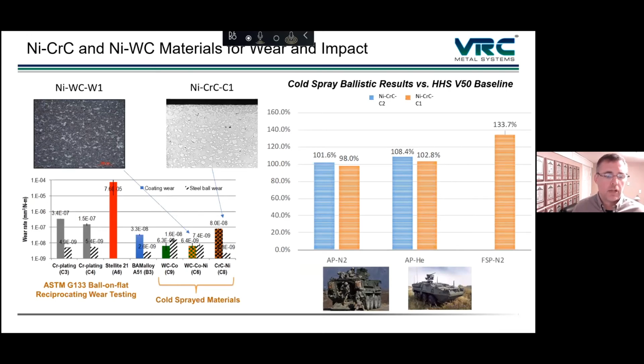ballistic performance as well. So this is repairing armor. This is high hard armor repair. And these are V50 type of tests, which means basically the 50th percentile will fail. So half of the samples will fail at that velocity condition. So what you can see here is we're actually getting an improvement when we use helium.